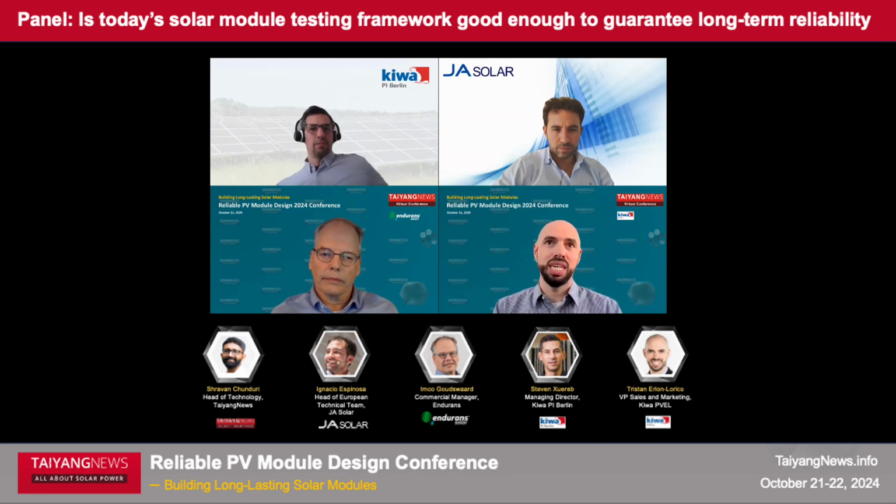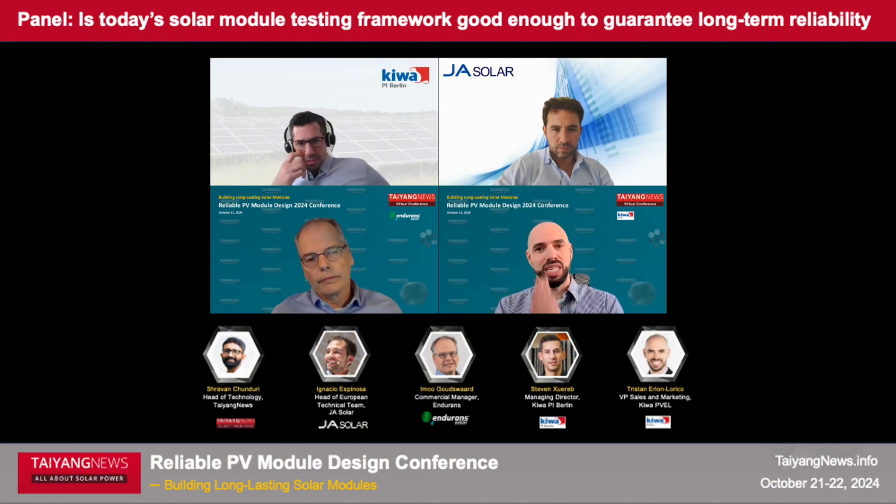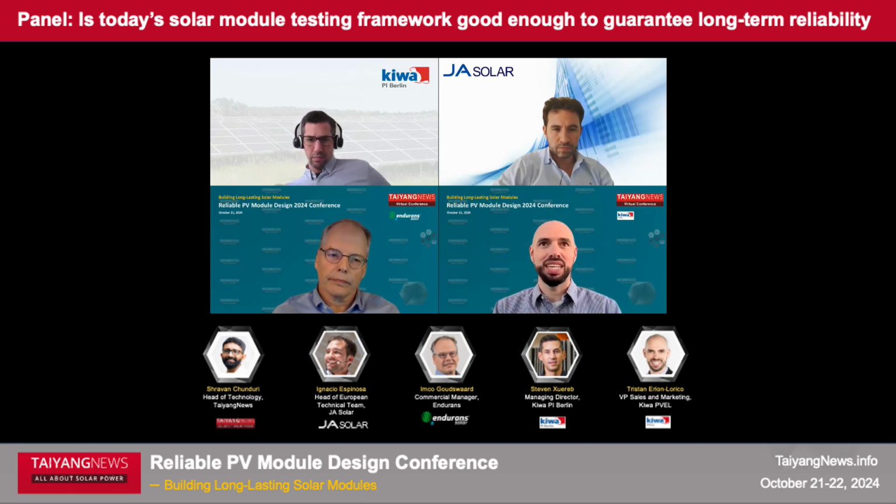And then in the mechanical durability, glass modules really protect the integrity of the cell. We don't see micro cracks in glass modules. Those are exceedingly rare. We've tried to create cell cracks in glass modules, and we're unable to do it without breaking the glass. But that said, the glass isn't as strong, and we find there's higher prevalence of module breakage for 2.0 millimeter glass modules. So I would say the mechanical stress sequence and the hail stress sequence are really the focus for glass reliability. And I think those are sufficient in showing which modules are done well and which aren't.